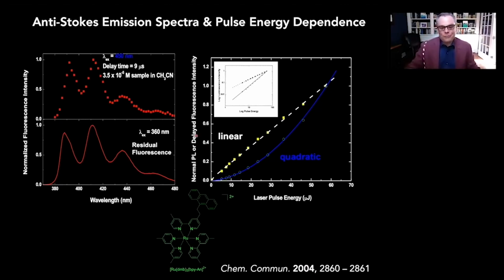And then similarly, if you excite in the blue and then turn your detector backwards, you can get the spectra of the delayed fluorescence, and clearly it's anthracene. There's also a little bit of unquenched residual fluorescence from anthracene in the same molecule, so you can excite it directly, and you see that the spectra match. So unequivocally, that's photochemical upconversion going on, resulting from a bimolecular reaction between two triplet energized bichromophores. Ultimately, this set the stage for everything that came after.